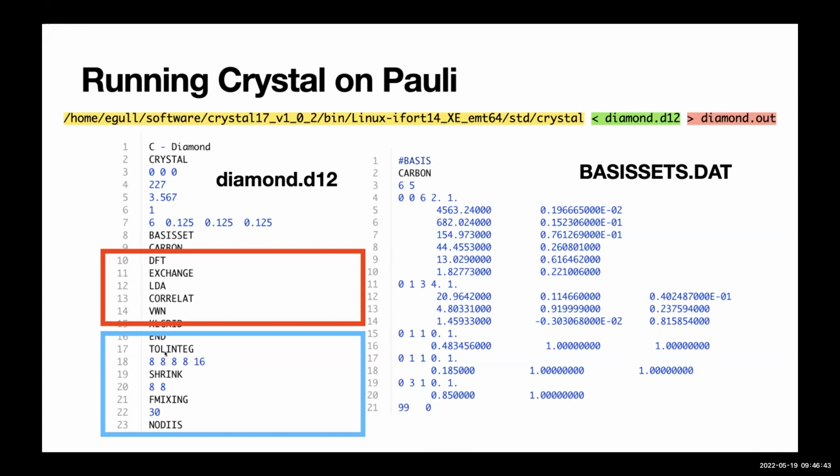In the blue box, we are inputting the computational parameters for convergence and accuracy control. This will include, for example, the tolerance for the total energy, the two-electron integrals tolerance, the mixing percentage of the Fock matrix, and the smear level, basically adding smearing for metals.